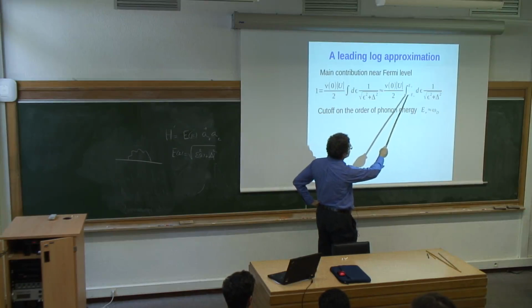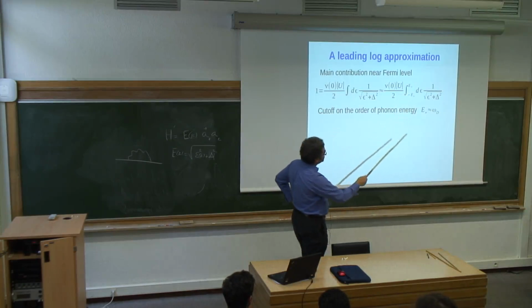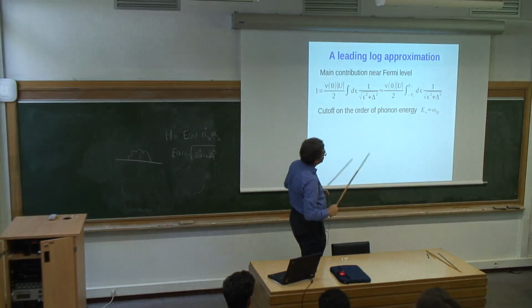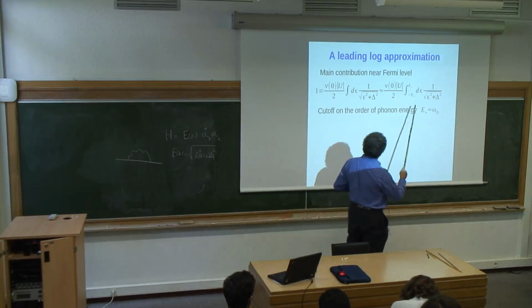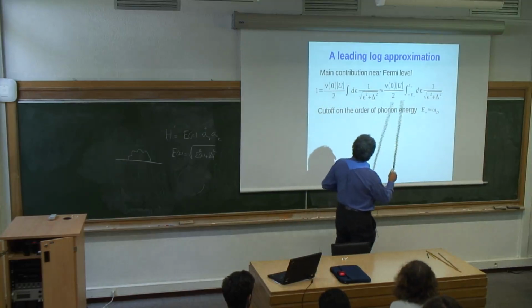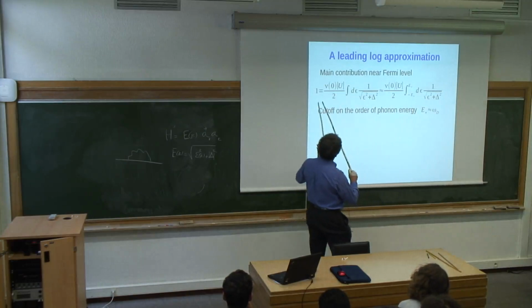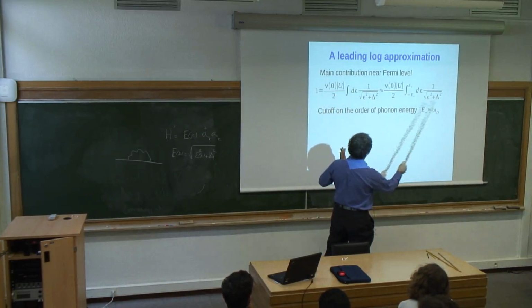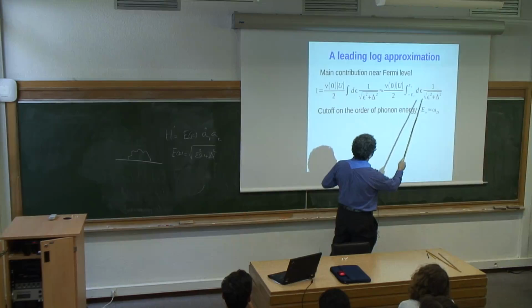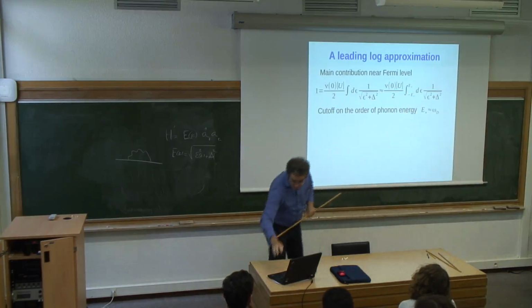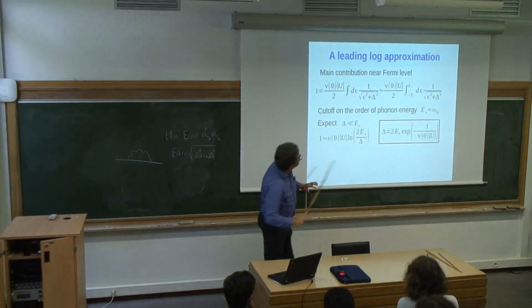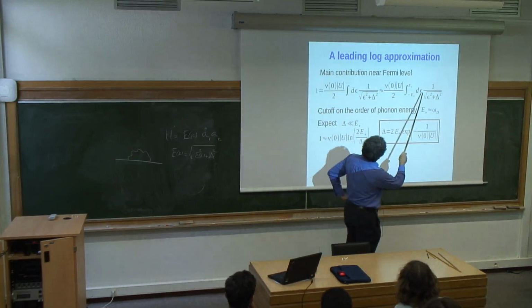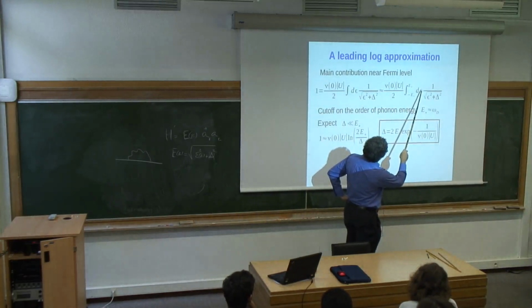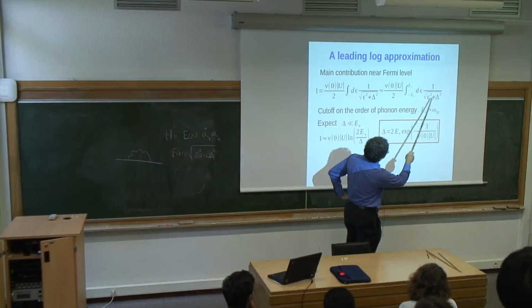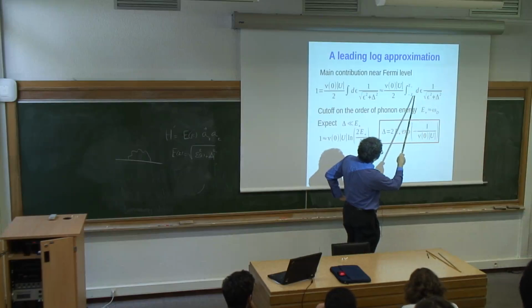And then I also account for the fact, which we knew and talked about but didn't introduce explicitly in the formalism, that only energies which are of order the Debye energy near the Fermi level contribute. And so then your self-consistency equation simply gives you an equation like that, where this is a simple integral that you can evaluate, and as you can see, this is basically d epsilon divided by epsilon. Forget about delta for the moment. So that's a log.